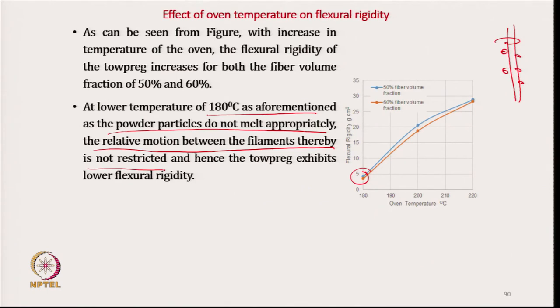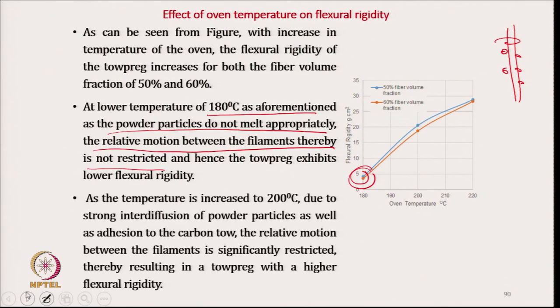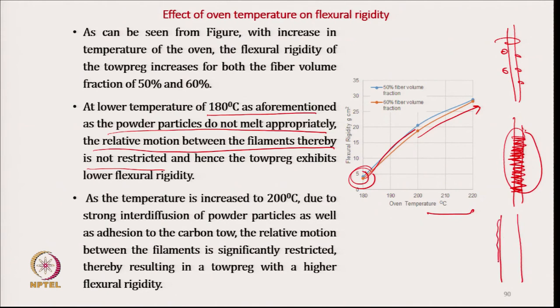So, towpreg exhibits lower flexural rigidity, but at higher temperature, what happened? These particles get melted and covered, as we have seen in the scanning electron microscope photograph, and due to this the bending rigidity, flexural rigidity, increases. It further increases as the temperature goes up to 220 degree Celsius, because at that stage, in addition to the surface melting, the polypropylene matrix penetrates inside the carbon tow. So, that helps in enhancing the flexural rigidity.